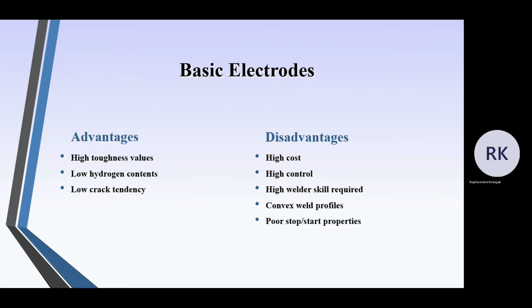So the basic advantages are high toughness values, low hydrogen content, and low crack tendency. But it is a bit expensive and difficult to control. A little bit of control is required, so welder skill is very important. You will get convex weld profiles and poor start-stop properties. So that's why welder skill and welder training are required a lot.